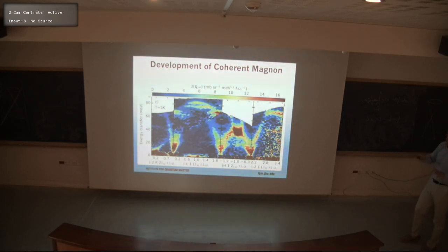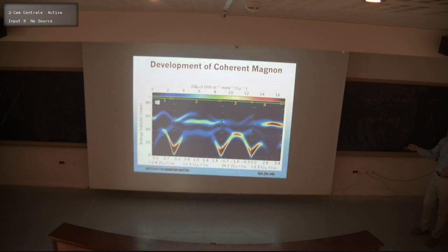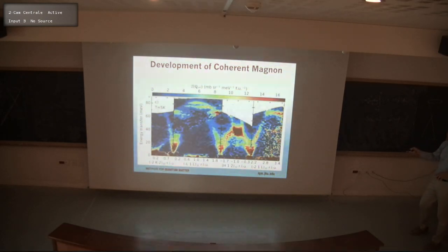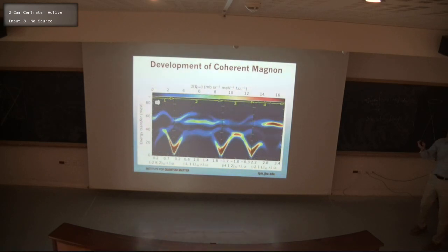And actually, then you can do something else. Rosa Valenti also looked at the exchange interactions in that now monoclinic state, using the same method of DFT, and then taking those exchange constants, we calculate the spin wave excitations, and you get this kind of pattern. So not so bad. It's not quite ideal. The bandwidth is not quite right, and so on. But I still feel it's really impressive that it's possible to get to that point.